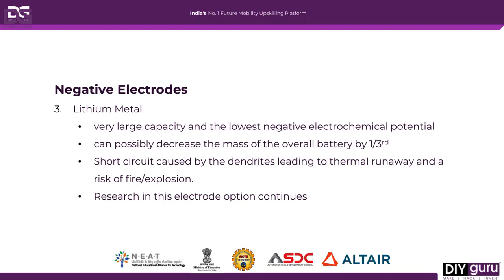Lithium metal comes out to be a very strong, desired candidate, but unfortunately lithium metal electrodes in secondary batteries have proved to be very challenging in whatever research or experiments have been conducted, because of the growth of metallic dendrites. These dendrites will short circuit and lead to thermal runaway, which intends risk of a fire or even an explosion as well. Nevertheless, lithium metal surely has potential. Research is going on in this area.